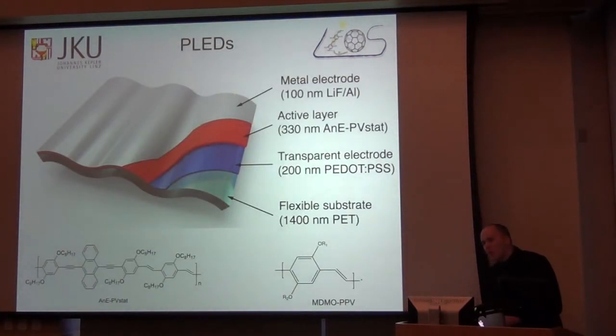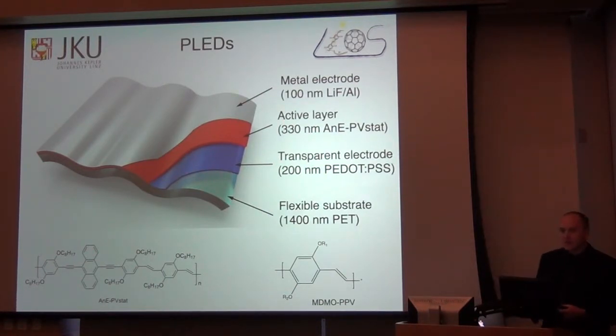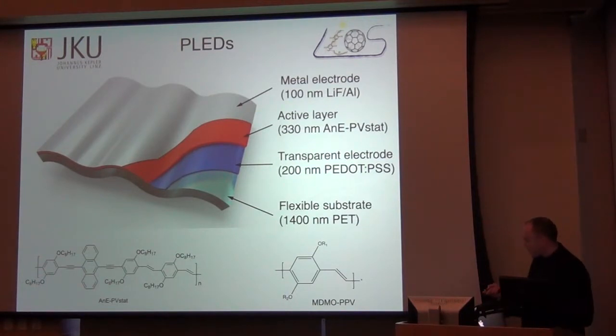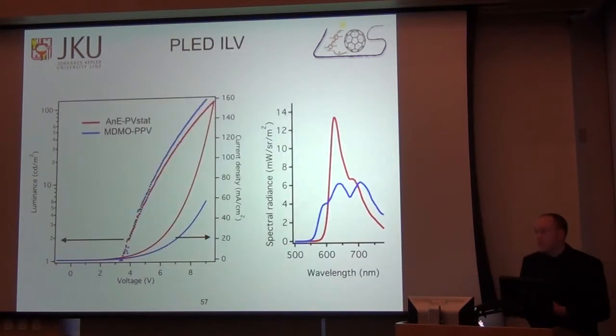As I mentioned before, an LED is not so different from a solar cell. So to manufacture LEDs on this technology is as simple as removing the P3HT:PCBM and replacing that with a single light-emitting polymer. In this case, we used either this in-house synthesized anthracene-containing AnE-PVstat polymer, or just this commercially available MDMO-PPV, which emits orange. So here we have a bright red emitter, and here we have an orange emitting polymer. We made two different colors at the request of the reviewers.